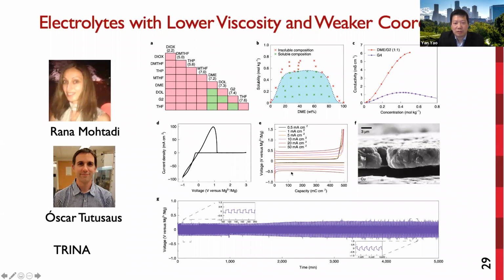In asymmetric magnesium-copper cells, even at 50 milliamp per centimeter squared, we can still reach a Coulombic efficiency of about 99.7%. The morphology of magnesium plated on copper shows a dense, smooth, and dendrite-free morphology. This is deposited at 20 milliamp per centimeter squared for an areal capacity of 3 milliamp hour per centimeter squared.